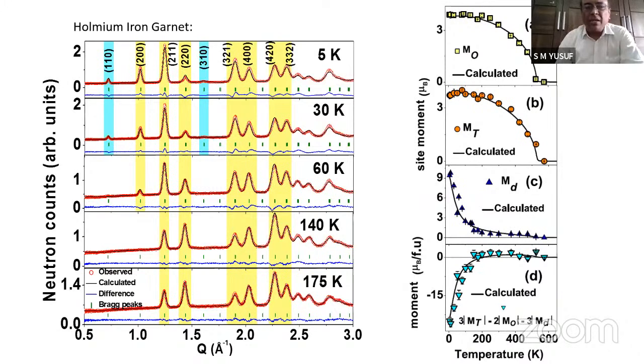Because garnet is something where you have three magnetic sublattices, as you know: octahedral site, tetrahedral site, and dodecahedral site. By doing neutron diffraction, and as you see, the growth of magnetic peaks, and also the addition of magnetic intensity at lower temperatures, we could calculate the ordered magnetic moment as a function of temperature of each and every individual sublattice, octahedral, tetrahedral, and dodecahedral. And each one we have modeled with the theoretically expected, that is the calculated one.